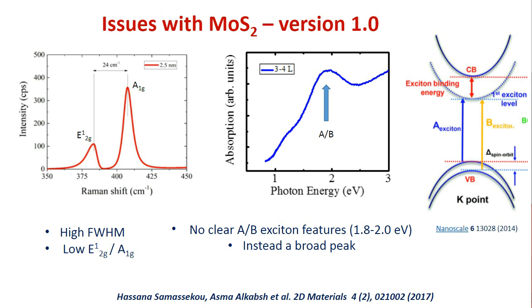Now the physics of this is a little bit hard to explain, but these peaks are excitons. Like the band structure we were talking about, the optical transitions are from an occupied band to an unoccupied band. The bands on the top are unoccupied bands. The 2 bands at the bottom are occupied bands. And if you do the math, there are at least a couple of transitions that we should be seeing at around 2 eV, and those are associated with what are called excitons, which are electron-hole pairs. So as far as characterization is concerned, we were hoping to see 2 peaks here, but instead we were looking at a single broad peak, which again pointed to disorder.